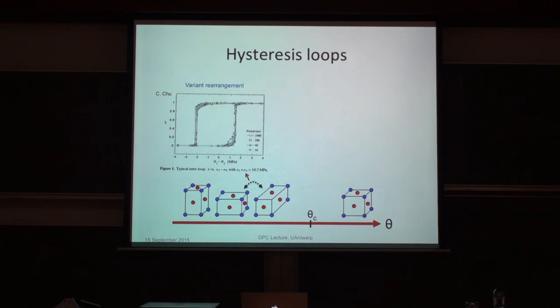So there's the possibility of going back and forth between this variant and this variant. That's done in some experiment here, and you see that this is some measure. You do it by stress. This is some measure of the stress. This is the fraction of this variant versus this one. And so you transform abruptly here. And then when you return the stress, you transform abruptly back. I'll show you how this experiment is done in a little bit more detail.